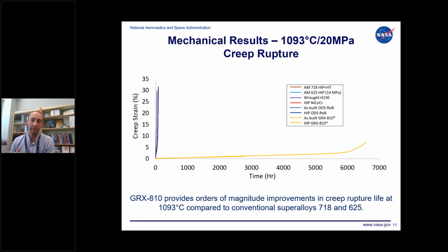The hipped version lasted to almost 6,600 hours, and we actually interrupted the as-built GRX-810 sample at 1% creep strain at 2,800 hours to better understand the deformation that was undergoing.